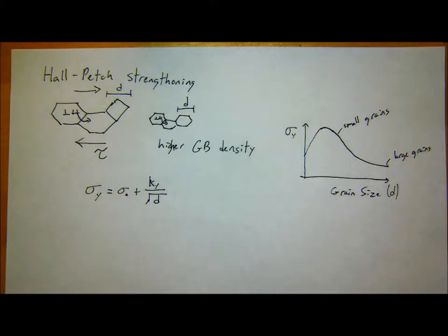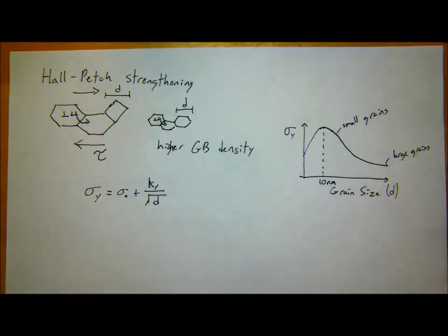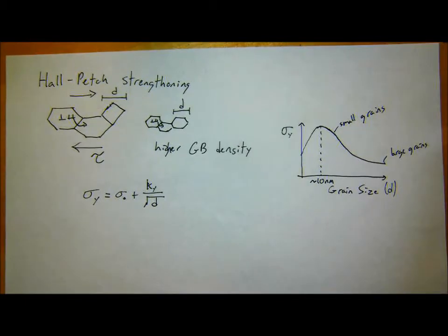You were on the right track, but it's not exactly grain boundary or dislocation sliding at the grain boundaries. This tipping point will start to happen actually at around 10 nanometers. So that's the magic tipping point where you get this weakening effect. And what happens is your grain boundary actually becomes a dominant volume fraction of your material. If you think about it, the crystal packing is dense. In the grain boundary, there's a low density of material because it can't pack in a perfect crystal. And so the grain boundary itself can slide easily. It's not necessarily dislocations in the grain boundary, but the grain boundary itself is weak. So the grain boundary doesn't necessarily fracture, but it can slip and slide, and it also depends on the angle that the crystals meet at.